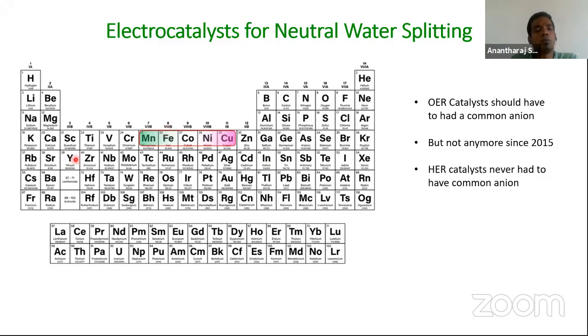All other metals either form a very strong bond with oxygen, I mean the metals which come before manganese. These metals form very strong bonds with oxygen, so that it makes the splitting of the metal oxygen bond so tedious that we have to apply additional energy, making it a less energy efficient catalyst. And the metals which come after form the metal oxygen bond very weakly, which means the adsorption free energy is very highly positive, so the reaction does not even proceed to the intermediate process. So these are the metals which have appropriate binding energy, I mean energy of interaction with intermediates. So we have to stick with these 5 metals.